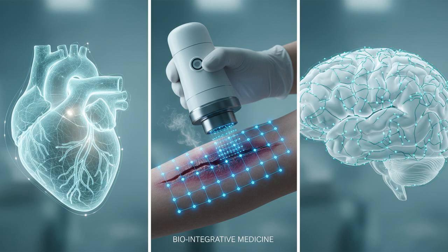The most immediate impact is in medicine. One of the most groundbreaking demonstrations involved researchers applying a monomer gel to the exposed brain of a mouse. They used a laser to draw electrodes directly onto the cortex. The electrodes formed an intimate, seamless contact with the brain tissue, recording neural spikes with clarity that rivaled penetrating needles, but without piercing the brain. This could lead to shrink-wrapped brain interfaces for treating epilepsy or controlling prosthetic limbs that grow with the brain rather than constricting it. Then there is wound care.